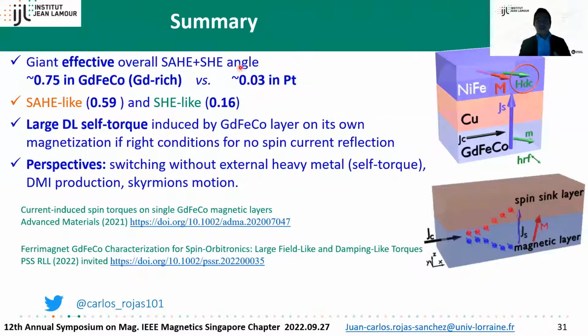So I reported in the first part a new characteristic temperature, the switching temperature, in this tungsten cobalt bilayer. And in the last part, I showed that gadolinium iron cobalt is a good spin current emitter. We have a strong spin-orbit coupling here coming from gadolinium, and we can explore different ways to exploit this. One is to look for the self torque in this gadolinium iron cobalt. With that, I would like to thank you for your attention.